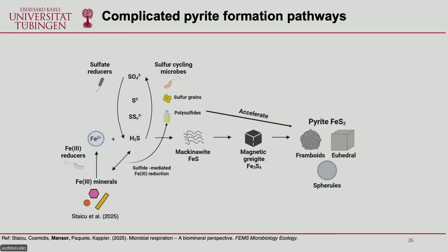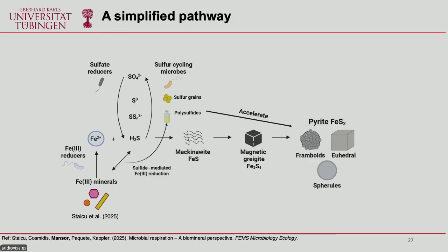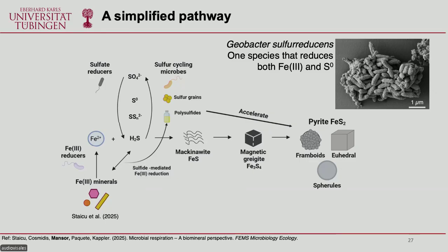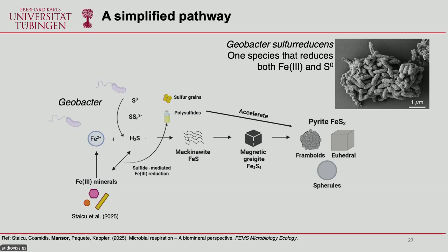So what we did is we came up with a simplified pathway in order to form pyrite. We use the same bacteria that can reduce iron, Geobacter sulfurreducens. As the name implies, they can also reduce elemental sulfur, and they produce hydrogen sulfide. And so we can essentially delete some of these pathways. We can simplify them. And then we have Geobacter that can produce both Fe(II) and hydrogen sulfide. And so we can do this somewhat easily in the laboratory. Okay, so this is our idea. This is our drawing board.